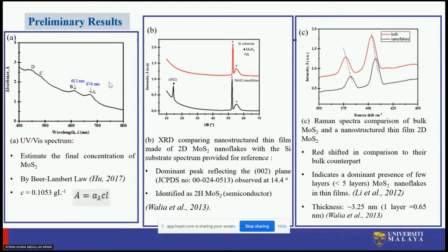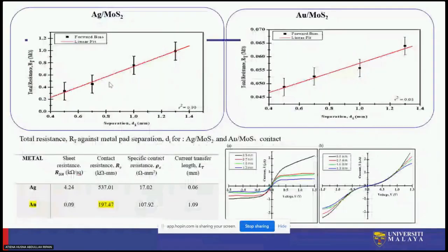And the next one is the Raman characterization. Both the Raman spectra taken from the bulk powder and nanoflakes were normalized, and it's found that there is a redshift in comparison to their bulk counterpart. Using the information provided by previous research, this indicates a dominant presence of few layers, less than 5 layers. Then we can make an estimation of the thickness of MoS2. It is around 3.25 nanometer, taking 1 layer to be equal to 0.65 nanometer. For TLM analysis,